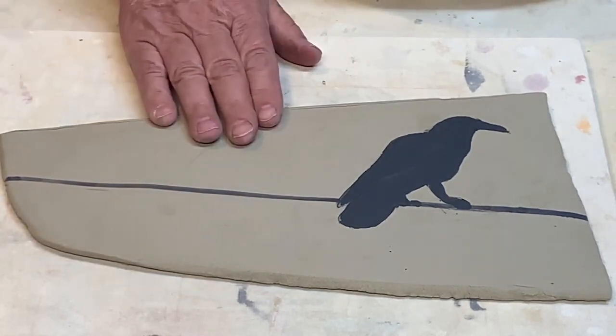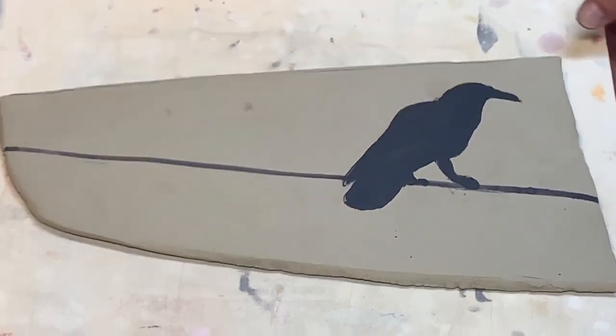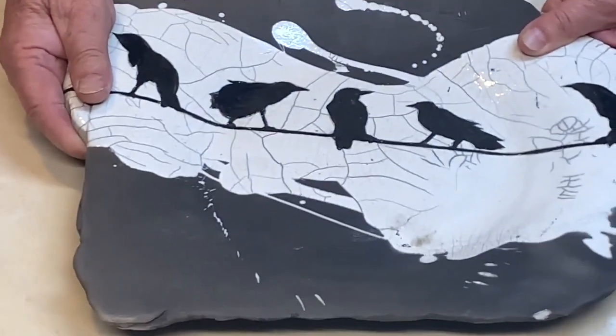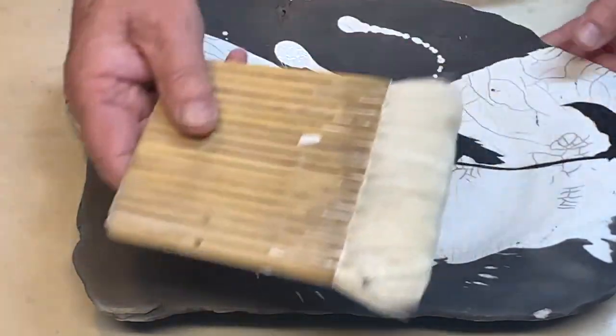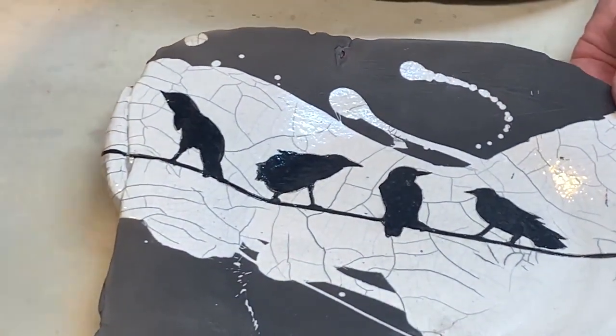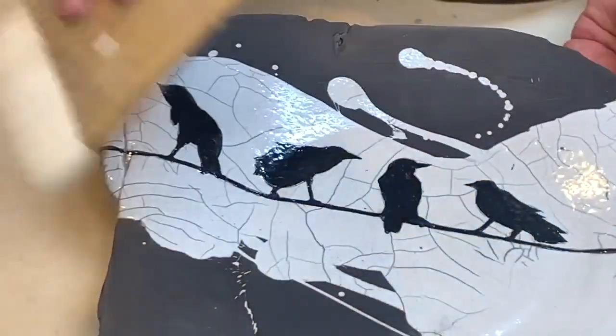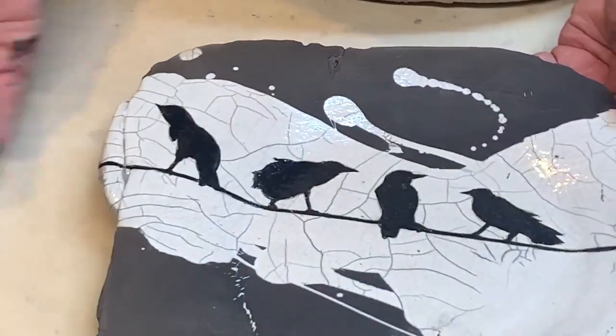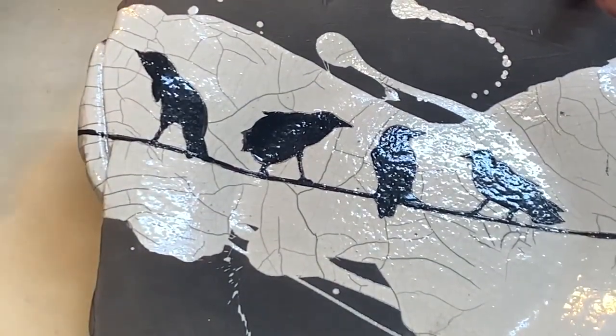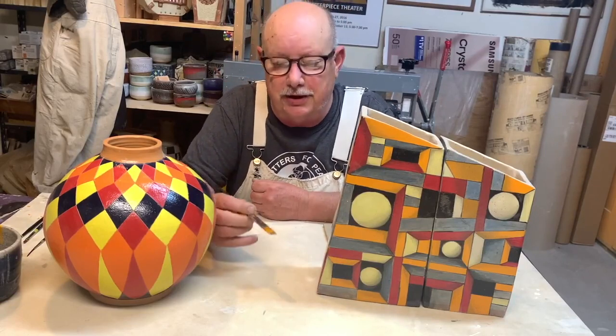I've given it three coats of under glaze with my round brush. Now what I'm going to do is let it dry out, bisque it to cone 06. Once it's out of the 06 bisque, I'll use my big brush, put it into the clear glaze, and just sort of slop paint it on. That's how I use my paintbrush then — I raku fire it. It turns the clay black and where it was glazed with my brush it turns white.